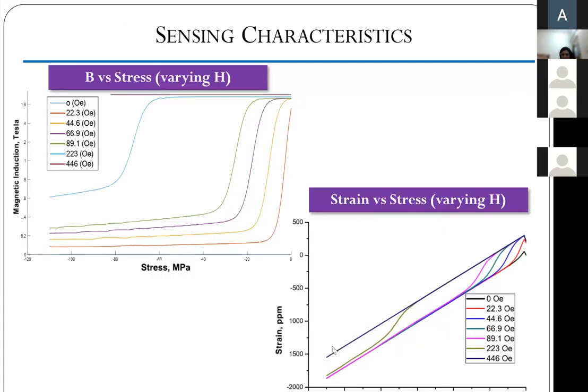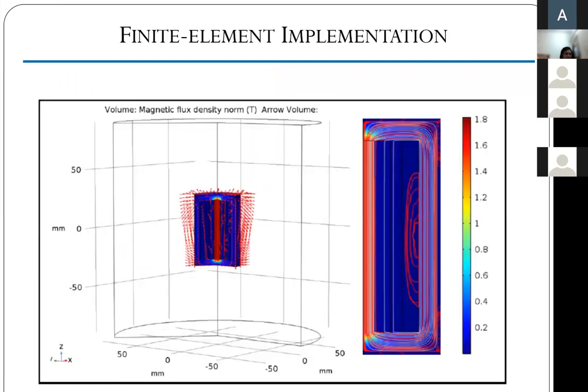What's interesting is that at the two bounds, meaning at zero magnetic field and after saturation, the behavior is straight, our typical linear elastic behavior, but in between, there is a non-linearity. Even in the stress strain plot, there is non-linearity because of the applied magnetic field. All of these results match very well with the experimental data that is available in literature. Given that we are out of time, I will stop here, but I just wanted to show that we were able to do this finite element implementation successfully using the model, and our results match with existing literature.